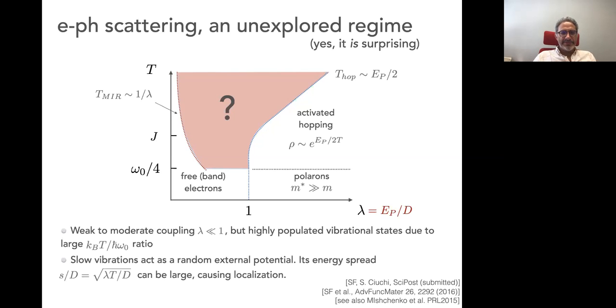So what happens is that even though the coupling of holes to vibrations is weak or moderate, there is such a high population of vibrational states, of thermal population, that this thing can be seen as a very strongly fluctuating environment. And you can actually calculate analytically the energy spread of these fluctuations in terms of the parameters of the model. And you see that this thing can be very large, even though lambda is small, if temperature is large enough. So you can have fluctuations that are of the order of the bandwidth.